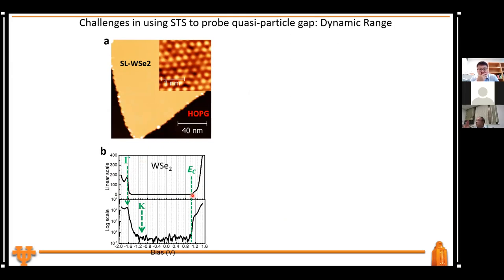In fact, in the early days almost everybody assigned that as the band gap. If you assign that as the band gap, then indeed the exciton binding energy would be around one eV. Right? But that is not the correct location of the band threshold. For the conduction band it is, but for the valence band, it turns out in this case the valence band maximum is significantly higher than what you usually observe right here. But how do I know that?